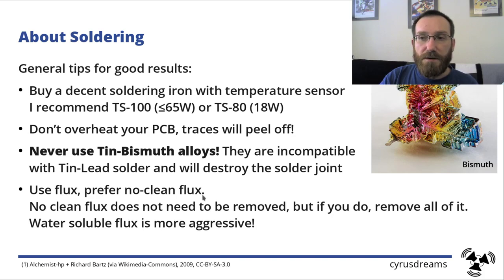You should prefer to use no clean flux. That one does not necessarily need to be removed, but if you want to remove it, please remove all of it, because there's not only rosin in there, what we in Germany call colophonium. Yeah, it's rosin, compared to resin, it's a very similar word. It's rosin, that's the actual stuff. But they also have activators to make that rosin more aggressive. And if you only remove half of the no clean flux, chances are that you have the activator still on the board and start to get corrosion.